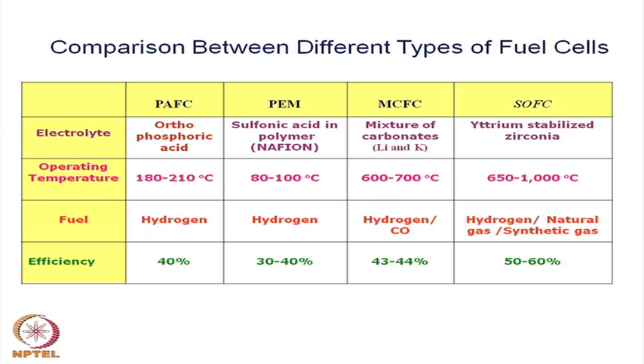So, there are certain advantages, although some disadvantages are also there, but operating a high temperature system is always difficult, and therefore, there is always a tendency to lower the temperature. So, we have at this point a group of solid oxide fuel cells, what is called LT SOFC or IT SOFC, that means low temperature or intermediate temperature fuel cells. IT SOFC means intermediate temperature, which is of the order of about 600 to 800 degrees, whereas LT means below 600 degrees. So, there is always an attempt to reduce the temperature of operation as much as possible.